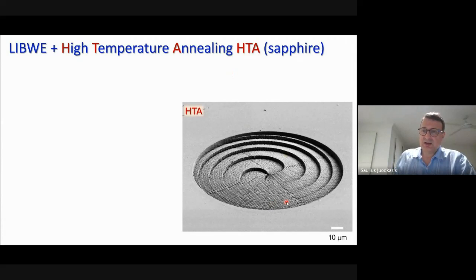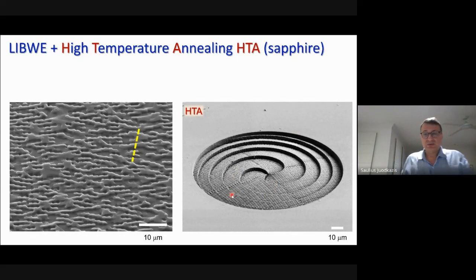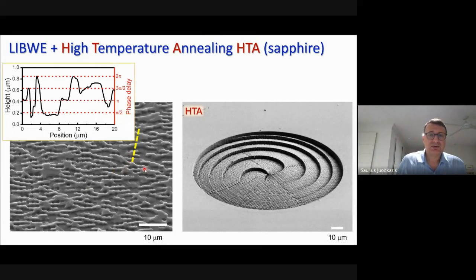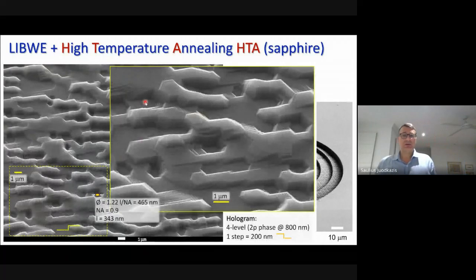And this structure is a big scale image of an optical vortex generator, which is really a structure with steps after annealing. And after annealing, we can make those surfaces not really as ablated light scattering surfaces. Here is an example of a diffraction optical element. And along this scanned line, you can recognize steps. The design was to have 4 steps to create 2 pi phase change, and this is the zoomed version after annealing.